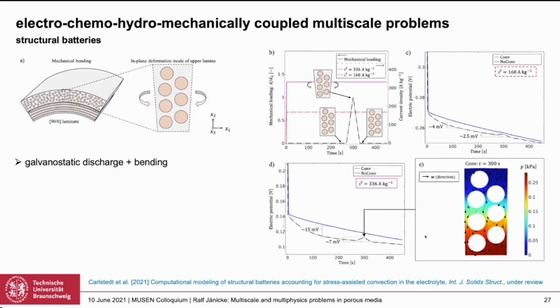And just without any equations here, just to give you an idea how it looks here, you see that's again a two-scale problem where this could be considered as an RVE. The fibers are here, and these pore structures are way smaller. The pores are of the size of 200 nanometers, whilst the fibers have a diameter of, let's say, 5 microns. And so if this is now undergoing a discharging current, basically, plus a bending at the same time, which is this peak. And now when we have compared models considering the convection of the liquid electrolyte, that's the black curve, and the blue curve is without this convective part, and you see then clearly that this is a relevant process here.